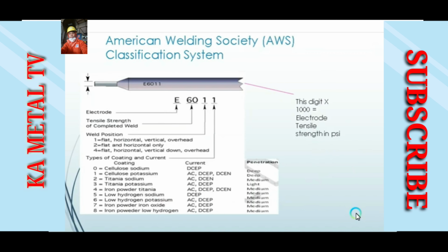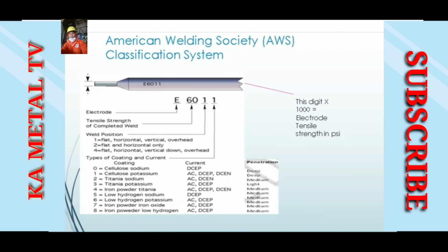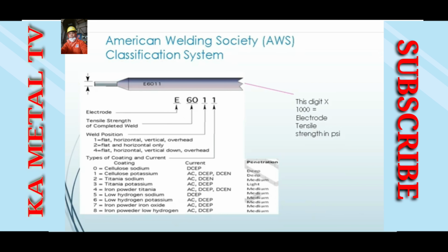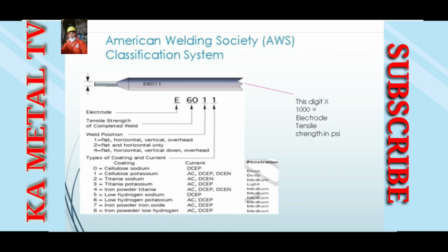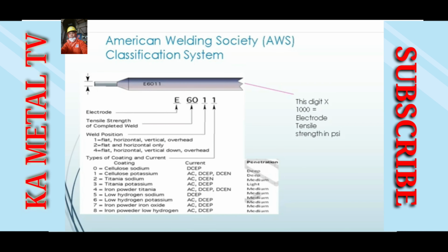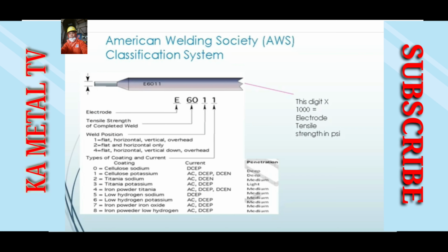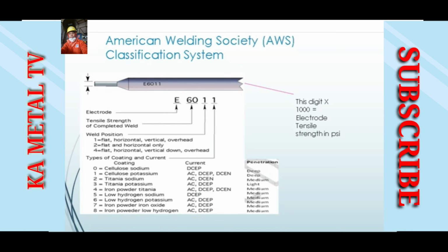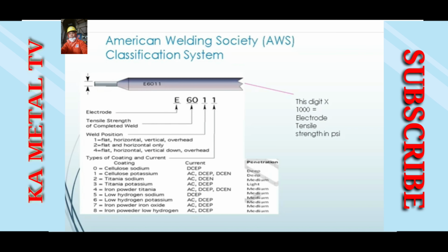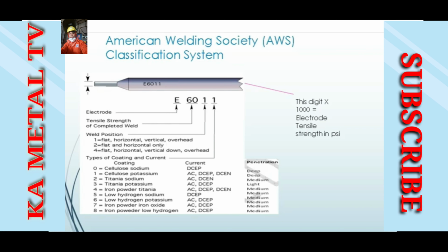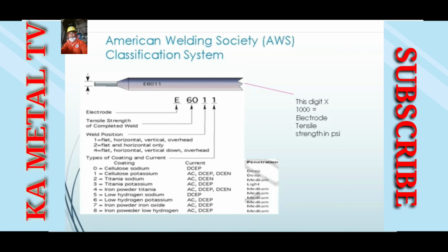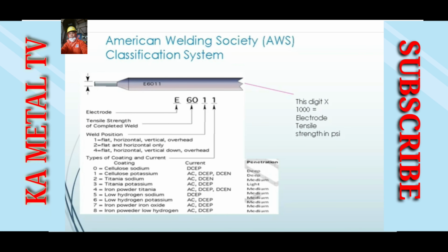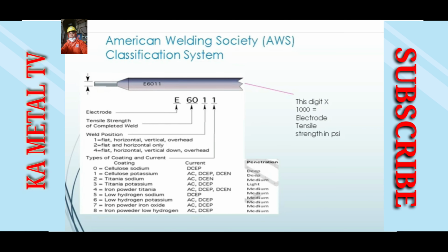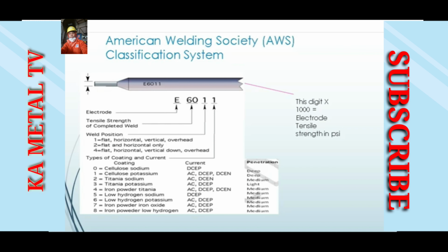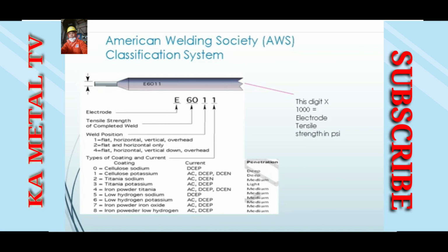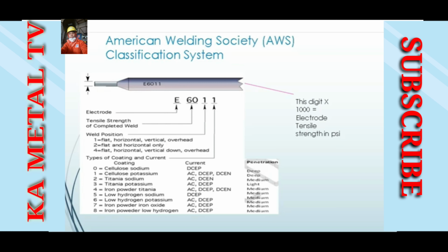Now let's understand the electrode classification system. By knowing it, we can know the properties of the welding electrode, such as its tensile strength, type of coating, welding position, types of current, penetration profile, etc. Here in this example, it's shown for E6011 type electrode. Here E stands for electrode. The next digits stand for the strength in KSI. Next, digit 1 means the electrode can be used in all positions. The last digit tells us the type of coating and type of welding current we can use. Here 1 means cellulose potassium, and this electrode can run on AC, DCEP and DCEN polarity. This electrode will give deep penetration.